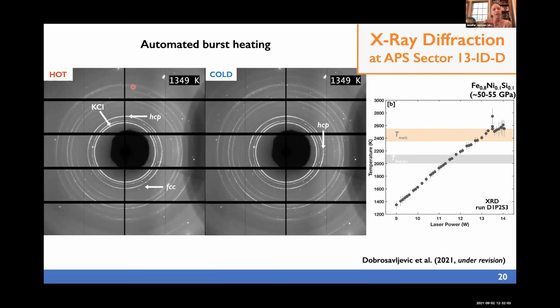So in this movie, I'd like to show, let me just get this. This is a movie we put together showing the evolution of the X-ray diffraction patterns. And what we've done here is use the automated burst heating mode at GSECARS, which allows us to have access to the background level of each pair of hot spectrum.